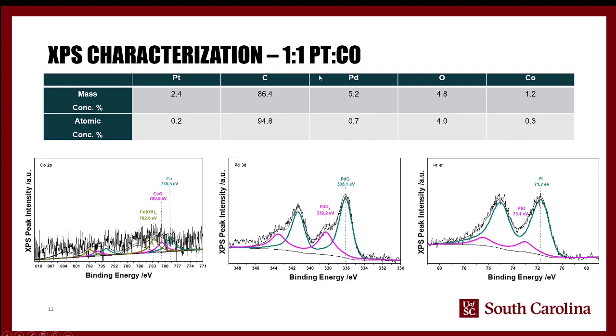Same thing here with the platinum and the cobalt. Again, the atomic concentrations are low. The cobalt signal is not fantastic, and so maybe we're reading a little bit too much into it at this point. But the same thing holds true here. The platinum is not significantly higher than the cobalt.